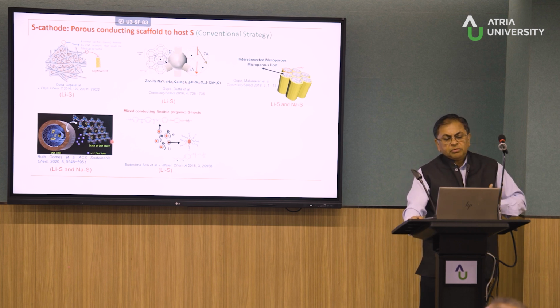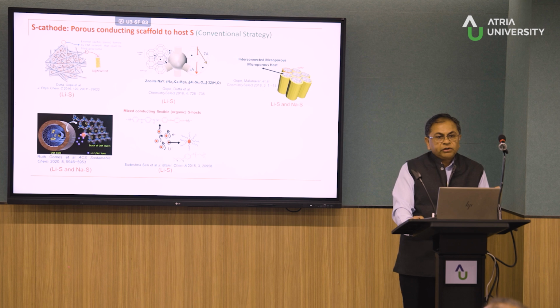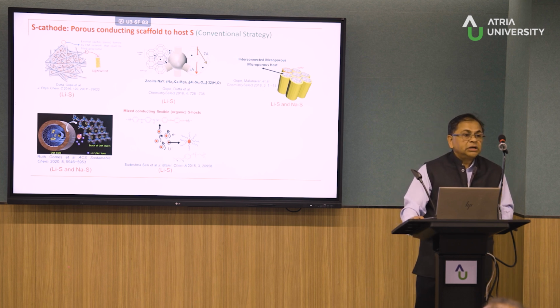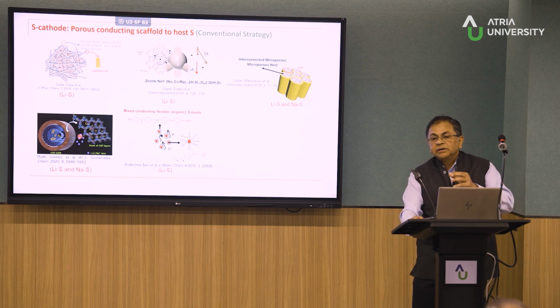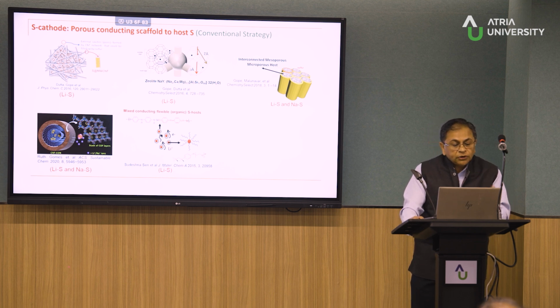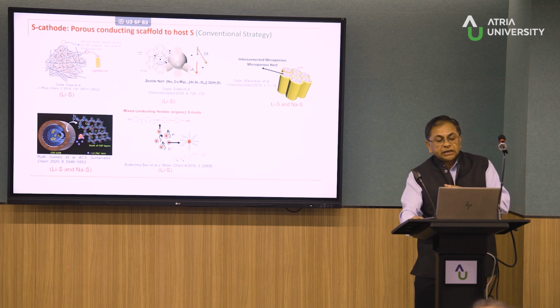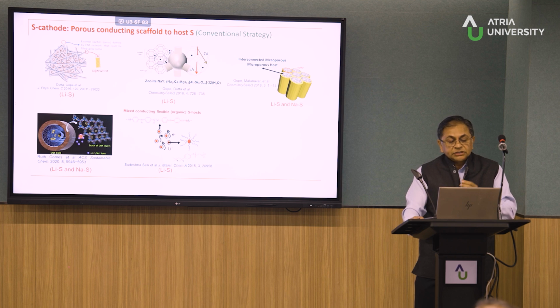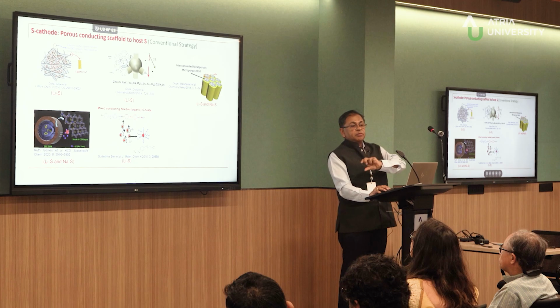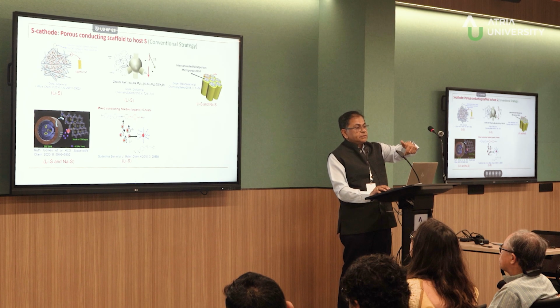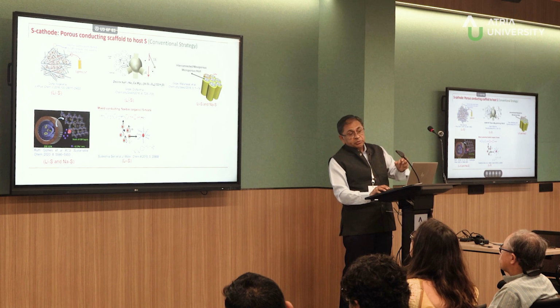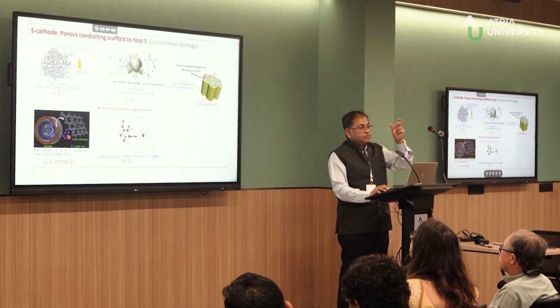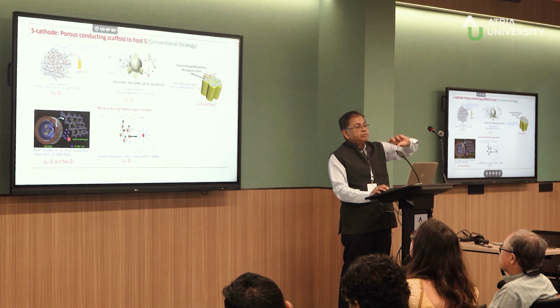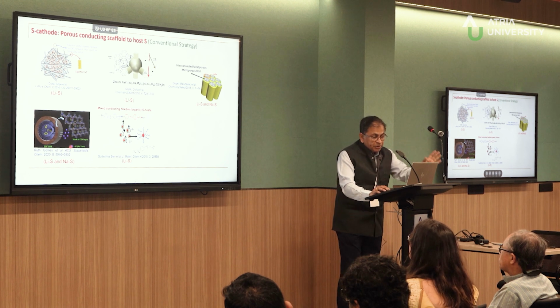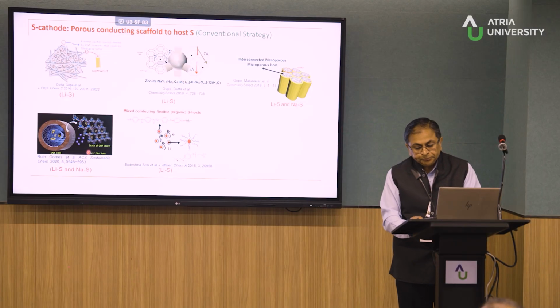But then, making even more complex systems like the covalent organic framework, we started to learn that the trapping of sulfur depends on which is your coordinating functional group, right? So it can be that the lithium from the polysulfide can be trapped on the surface, okay, on the host, or it could be, if you have something else, the sulfur of the polysulfide getting trapped to the host. So the trapping mechanisms are also very unique.